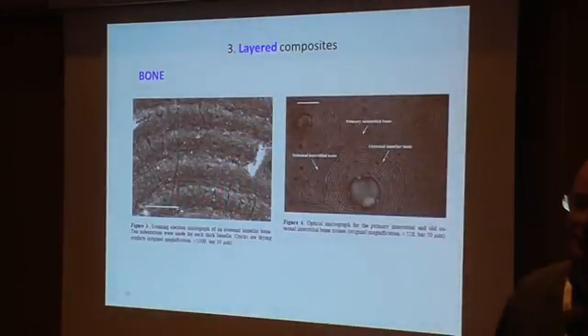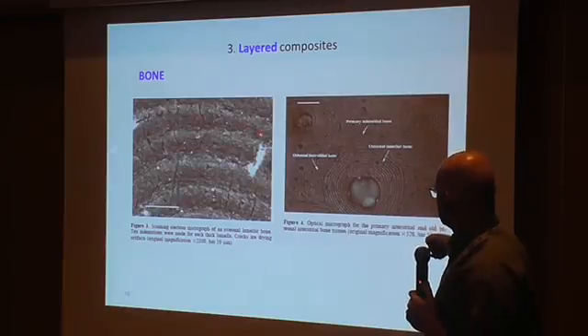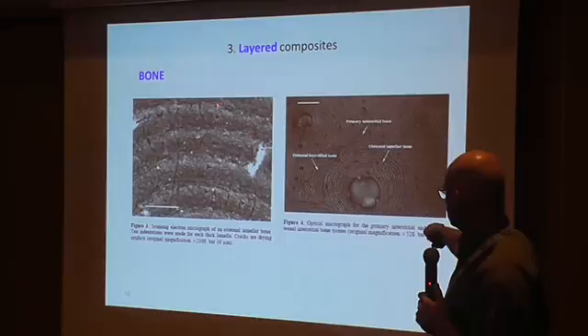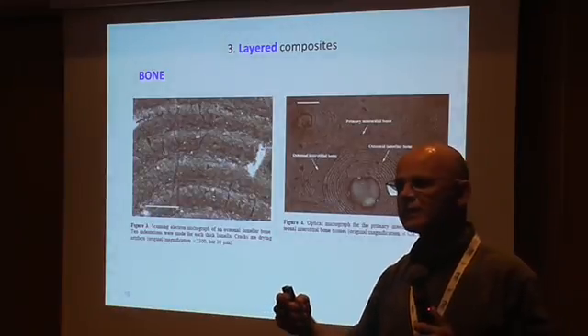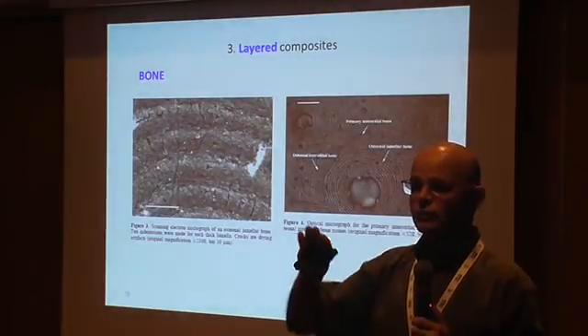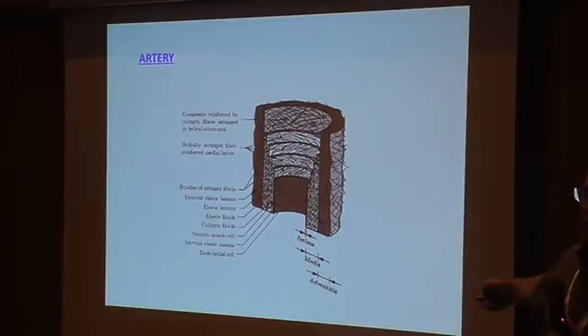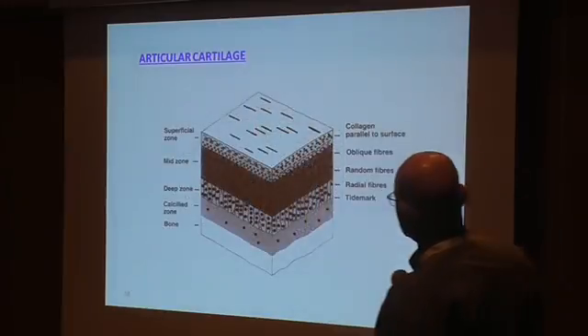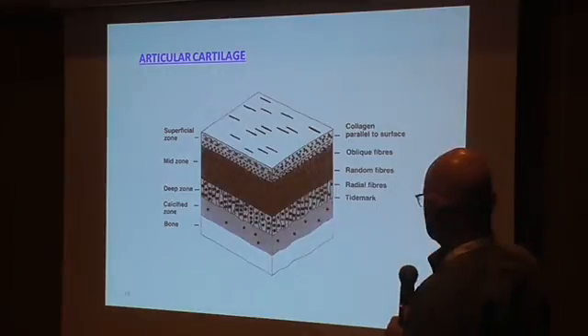A third example is layered composite materials. Layering occurs, for example, in bone. Bone is made of lamellar osteonic bone, which forms layers about five microns thick. Every layer has an array of hydroxyapatite platelets oriented in a different direction, giving a rotated plywood arrangement, which is very complicated and interesting. Artery is another layered material, extremely complicated, divided into intima, media, and adventitia with many intermediate layers. Cartilage is even more complicated — not symmetric in thickness or fiber direction.